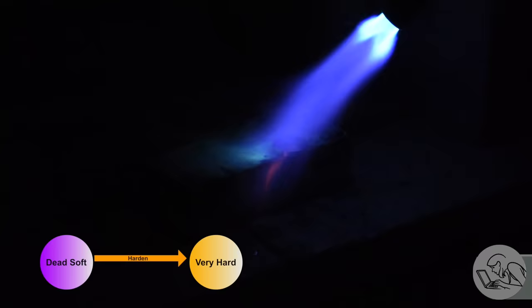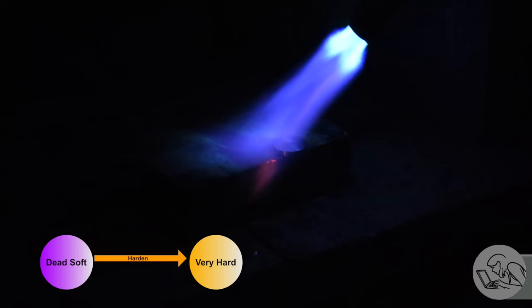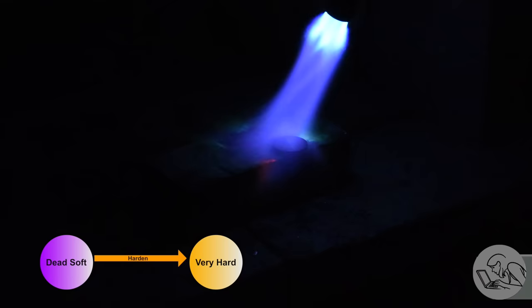And away we go. I'm going to do this in the dark because torch hardening and tempering is all about color and it's easier for you to see the color on camera if it's dark. For the hardening process, all we're trying to do is get it up to a glowing, what people call cherry red or kind of an orangish red. Anything in the bright red to orange color spectrum is going to be fine. When you see that bright orange color, you want to hold it there for a good several seconds.